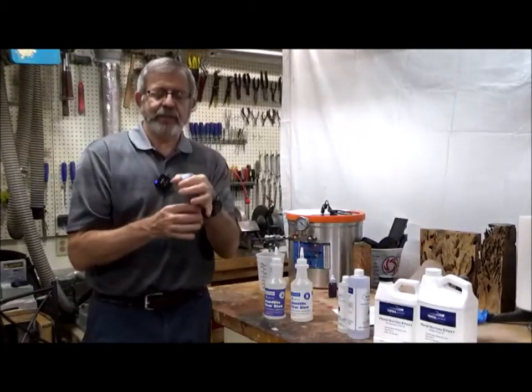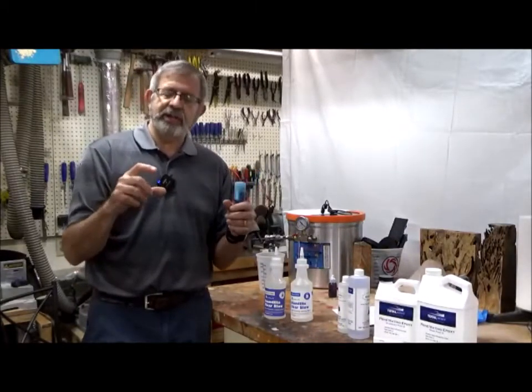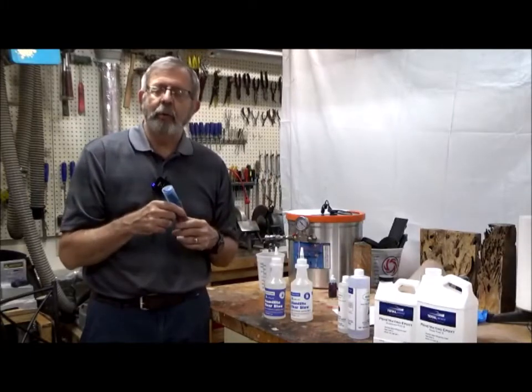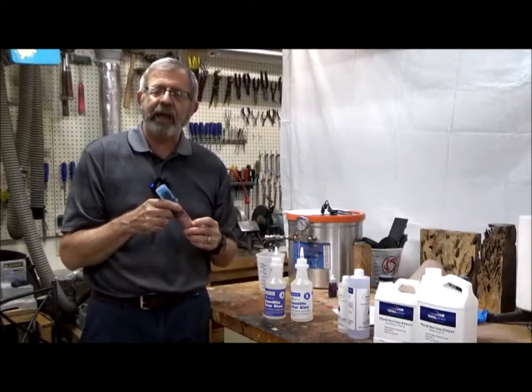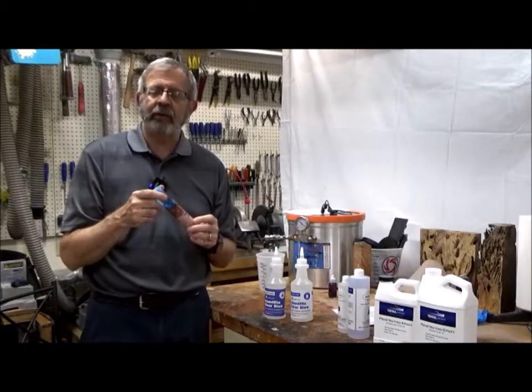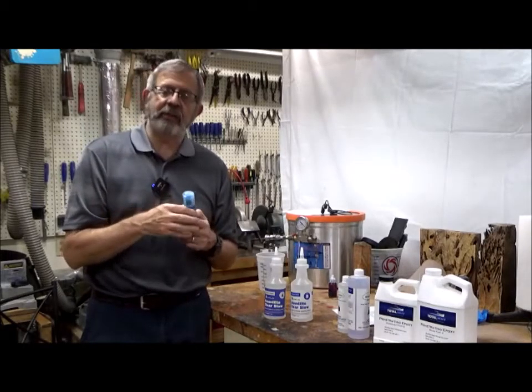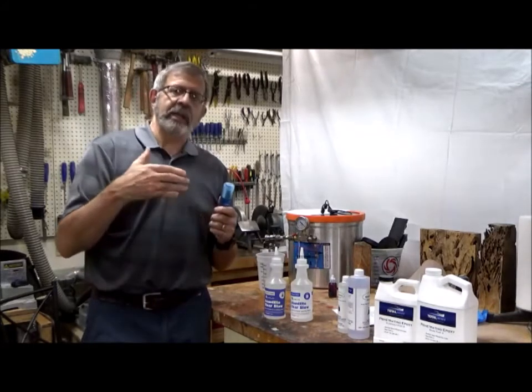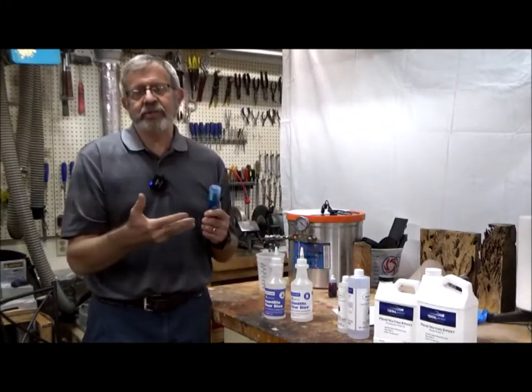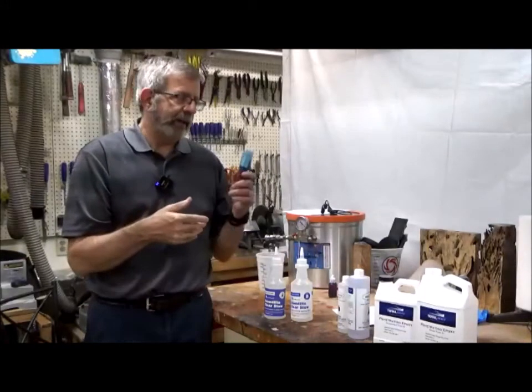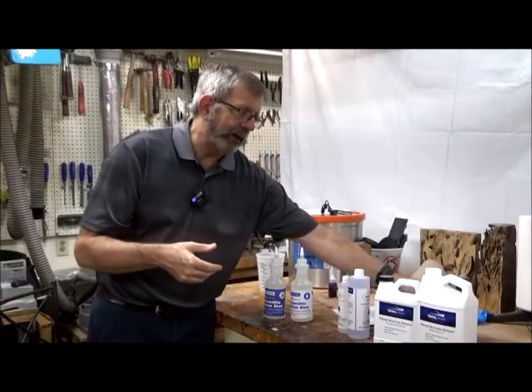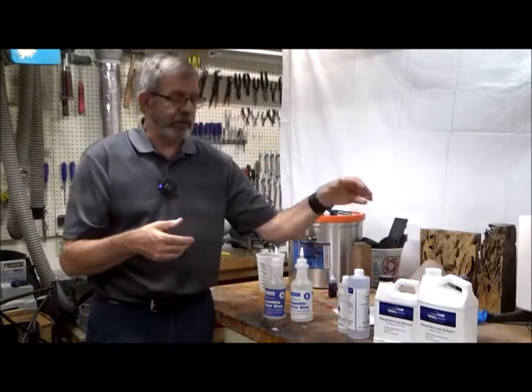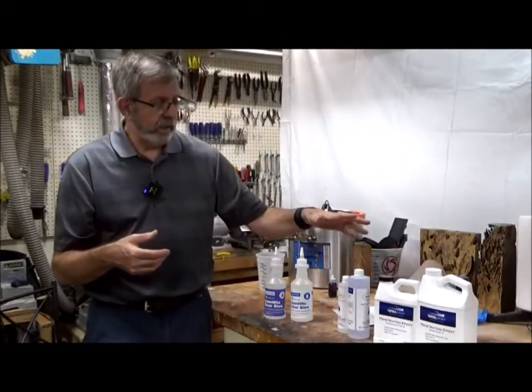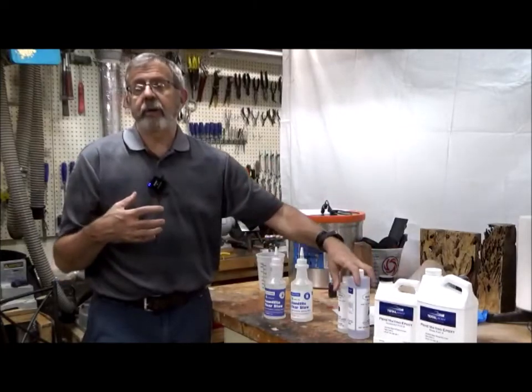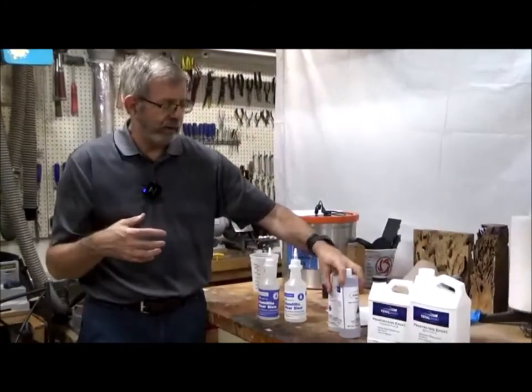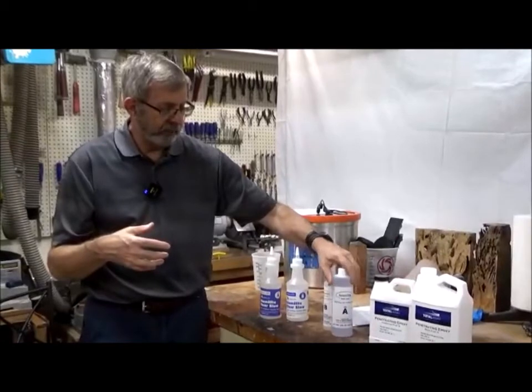It's not a problem when you have something this thin, but if you had a large piece that you're pouring more than an inch thick, it's very prone to cracking, to have a thermal crack get into it because of the heat that's generated. The way you mitigate heat generation is you have it cure very, very slowly. And so you have to go from the polyurethane resins now to the epoxy resins. So there are a number of epoxy resins out there for different applications.